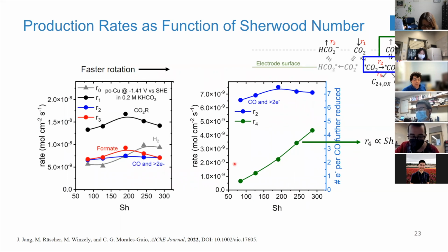So here what we're saying is the change of selectivity. Here the selectivity is changing towards carbon monoxide. It's not that copper is not good at making CO, it's just that it makes CO and you cannot remove that CO fast enough, because you're limited by the desorption and the solubility. But it's plenty active to make CO.